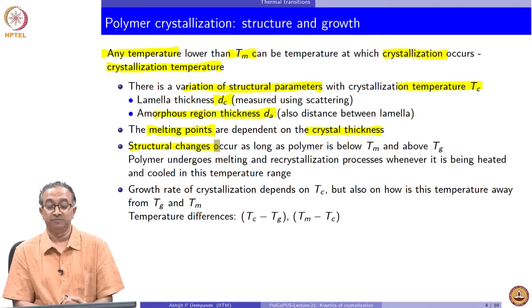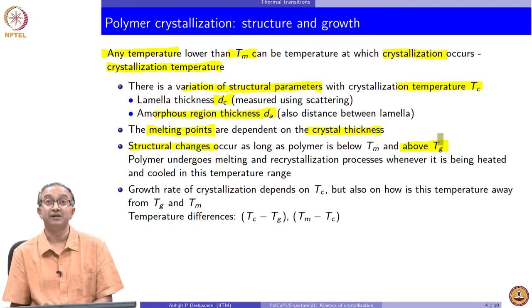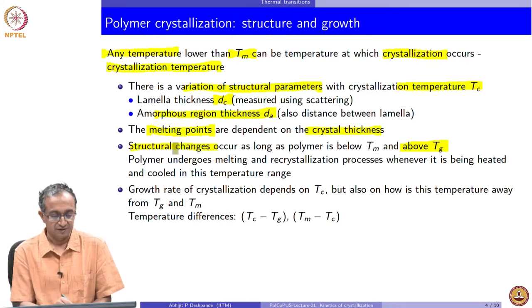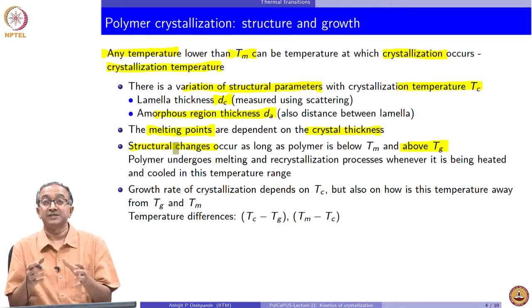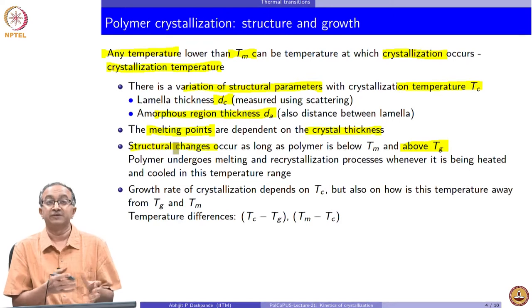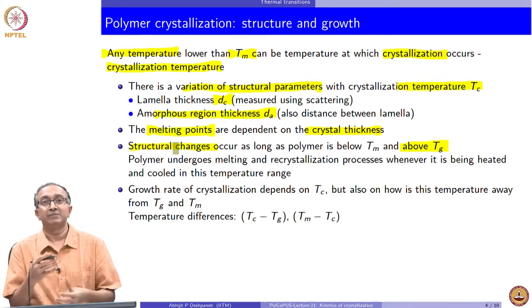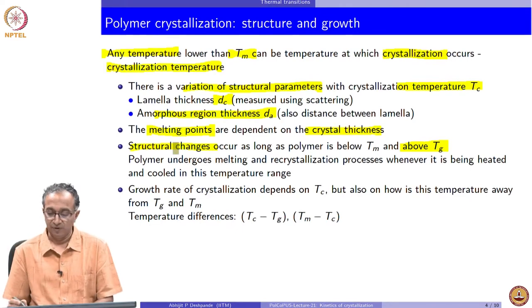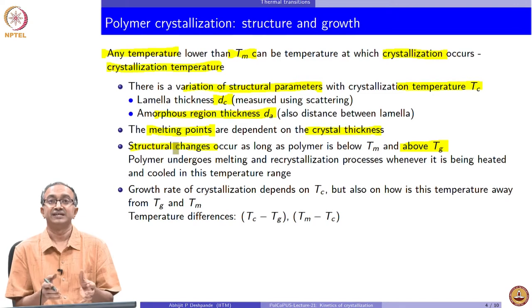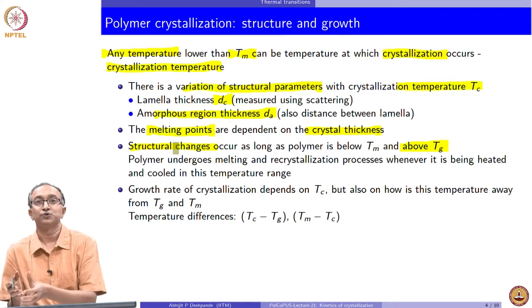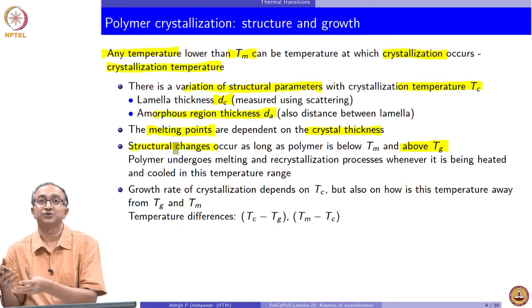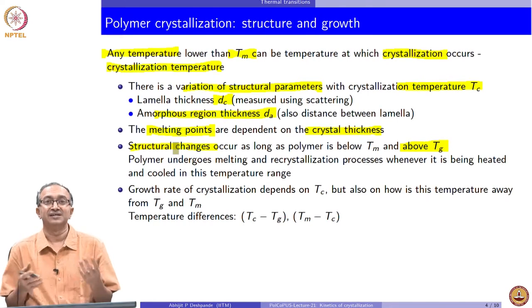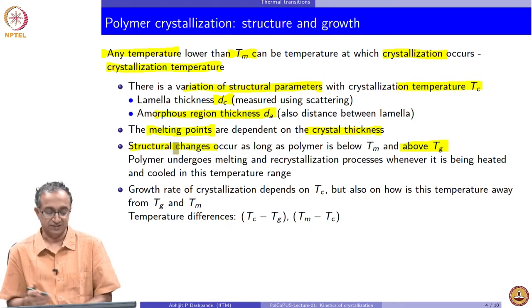Another complication in polymers is that as long as segmental flexibility is present — meaning we are above the glass transition temperature — structural changes can happen. If I keep a sample close to but below the melting point where segmental mobility is present, crystals can melt and reform repeatedly. For example, if PET crystals are made at 160 degrees Celsius and then the sample is heated to 200 degrees Celsius, some crystals will melt and reform, giving a completely different structure at 200 degrees Celsius.